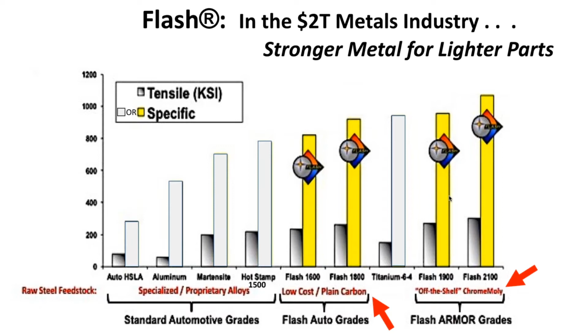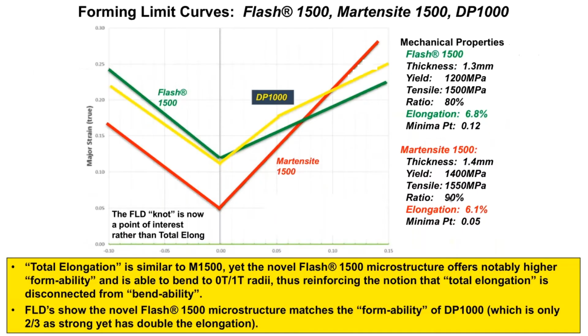Yet we took that material and made it into something pretty darn interesting. Forming limit curves are always important when you're doing simulations on can you even make the part. This work was done by Hyundai and a gentleman by the name of Danny Schaeffler, who's highly respected in Metro Detroit for making FLDs. The red curve shows the FLD for martensite 1500, the green curve for flash 1500, and the yellow curve for DP 1000.